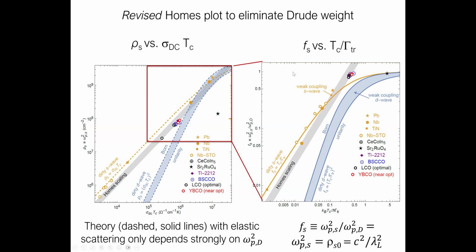And so we decided that a lot of this is David Broun's insight, a lot of the dispersion of the data along this line comes from the fact that all of these samples have wildly different Drude weights. So it's interesting to try to scale out the Drude weights of both axes here. And what you get when you do that are two different scaling variables. This is called the superfluid fraction. It's the superfluid plasma frequency squared divided by the Drude weight squared. And then this is Tc divided by the transport rate.